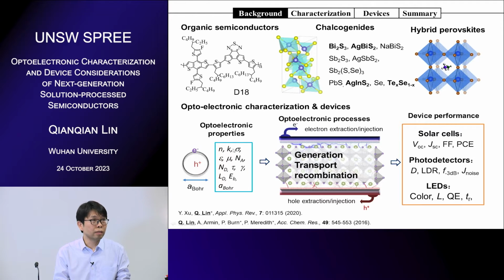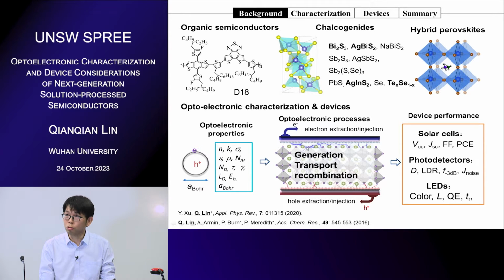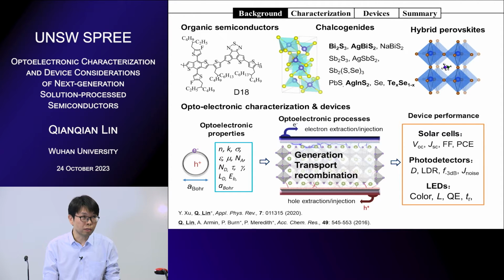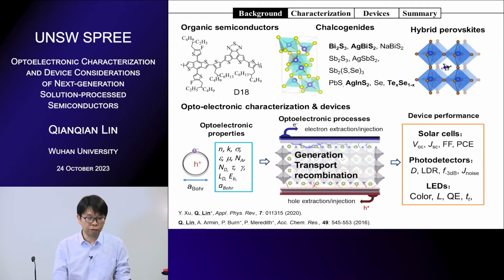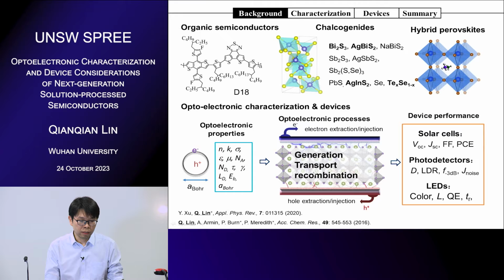And after measuring so many physical parameters or properties, we then move on to the devices. So we'll test the optoelectronic processes within the device. We use operational devices and test the charge carrier generation, and we look at the generation yield. After the carriers, electrons and holes, are generated, we look at how the carriers diffuse and drift within the active layer. Then during the charge transport, the carriers may recombine with each other. Holes will recombine with electrons and emit photons, or they can be trapped by the trap states. Then we will get efficiency losses.